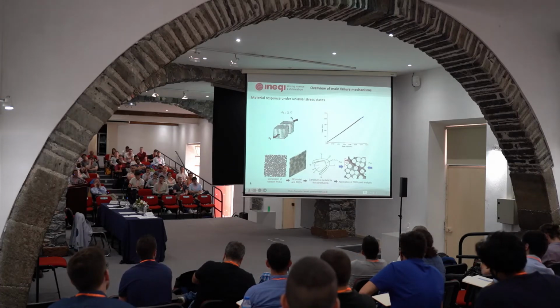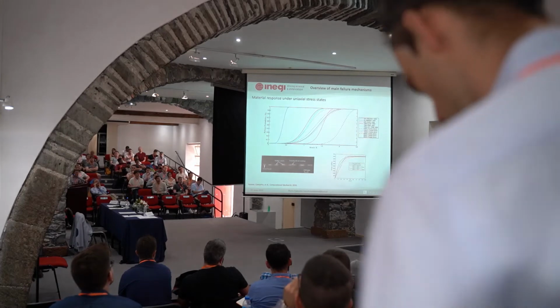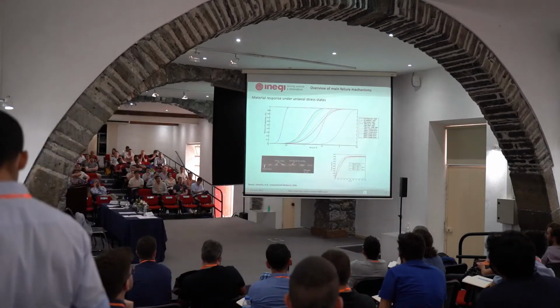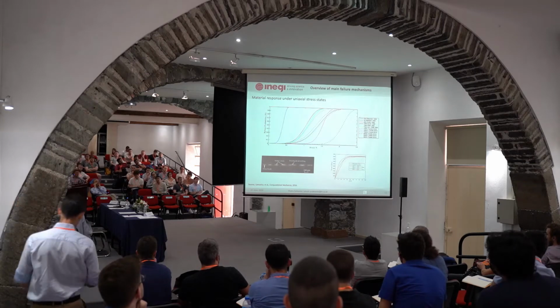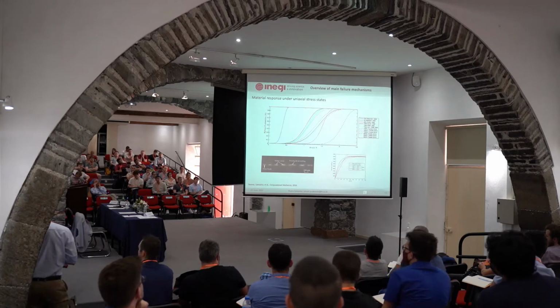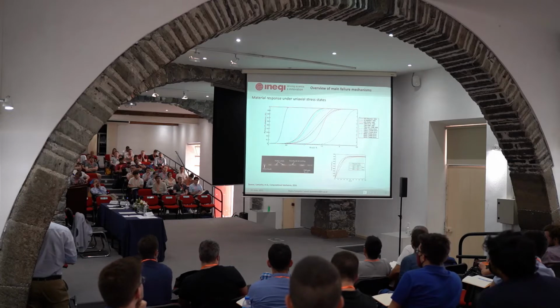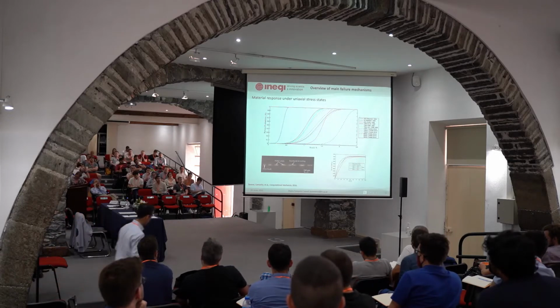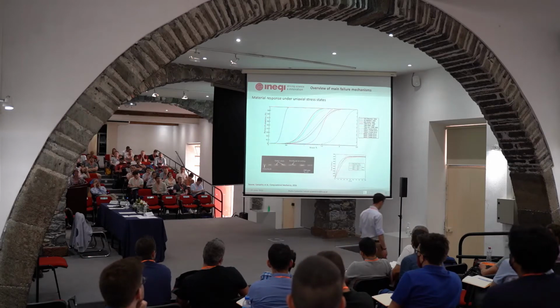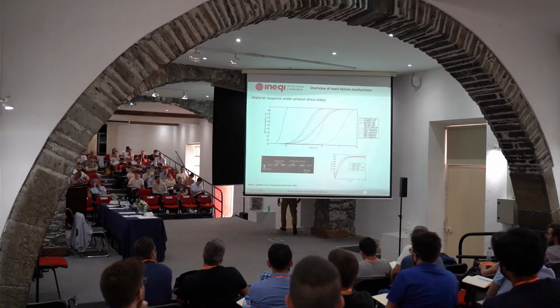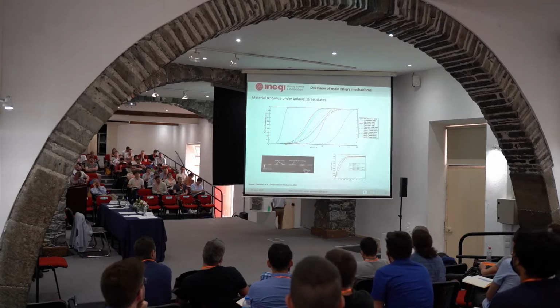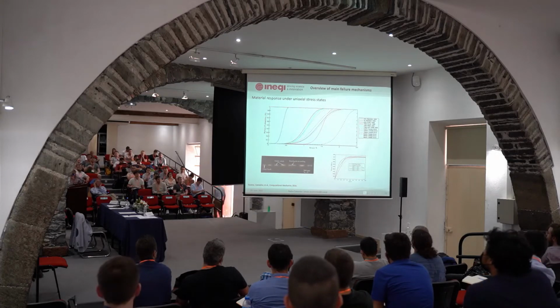For example, if we want to apply transverse compression, we'll end up with this failure pattern. You have a stochastic distribution for the fiber strength. So you have here, for different types of carbon fibers, the relation between the applied strain and failure probability. This is the first thing that we need to understand when we want to simulate longitudinal failure, in the sense that I cannot put the same value of strain for the fibers. I have to rely on the appropriate distributions of the particular fiber that I am using.